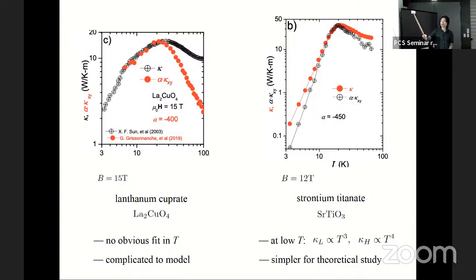And in these two materials, we chose to analyze this strontium titanate material first, because first of all, this material is simpler, so it's simpler for theoretical study. And moreover, the data is cleaner. The kappa L goes as T cubed, as you would expect for a simple phonon thermal transport. And the kappa H goes as T^4, also very clean data. That one is much more complicated. So we decided to understand this one first. Okay.